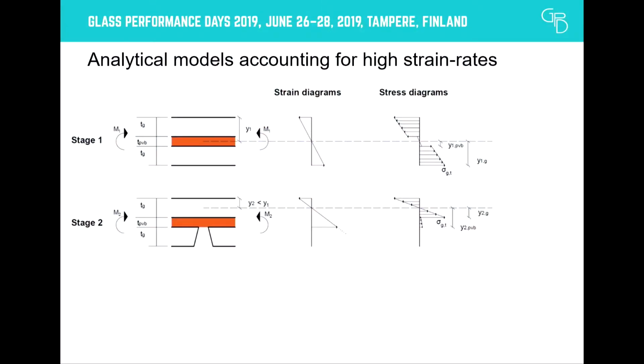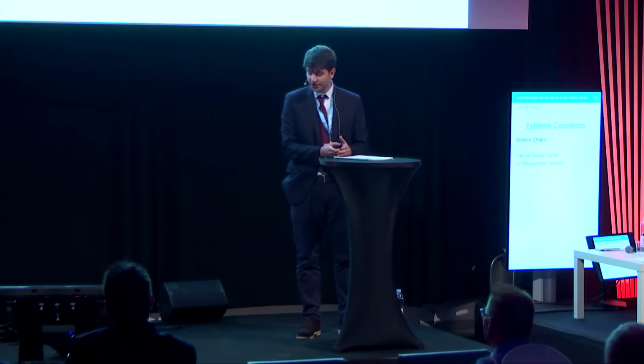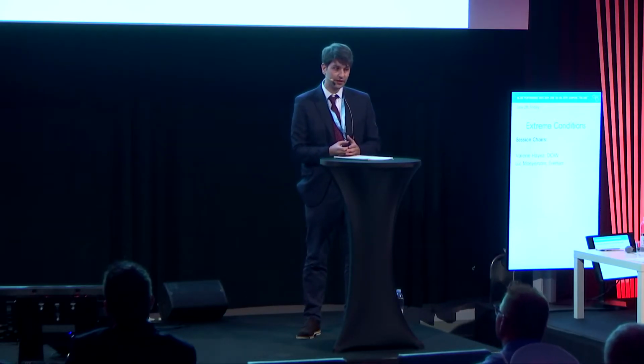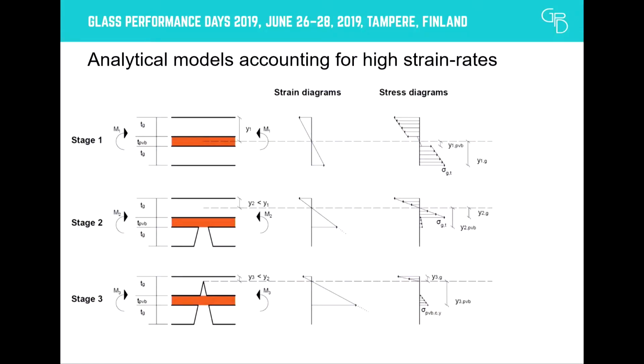When the glass layer that is in tension first fractures, the second stage will commence. At this point, the residual bending capacity is provided by the remaining unfractured glass layer and the interlayer. It is, however, considered that the contribution of the interlayer is negligible due to the higher stiffness of the unfractured glass layer. The third stage considers that both glass layers have fractured, and the composite bending response is provided by the attached glass fragments that come into contact and generate compressive stresses, and the interlayer in tension.